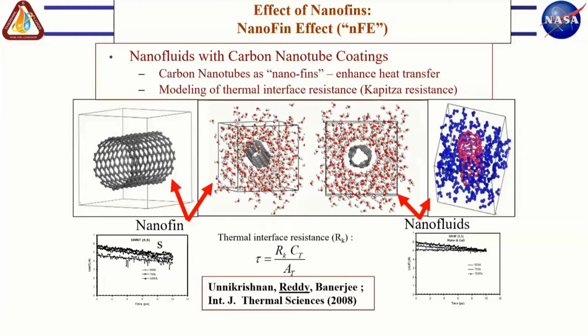And then you give sufficient kinetic energy to the nanofin that it goes up in temperature. And then you see how the temperature decays with time as the crystal lattice of this nanofin interacts with these vibrating molecules. And so this decay curve of change in temperature with time, which is shown in the bottom left and the bottom right, that's your rate of change of temperature with time, or what we call the tau in this equation on the bottom.